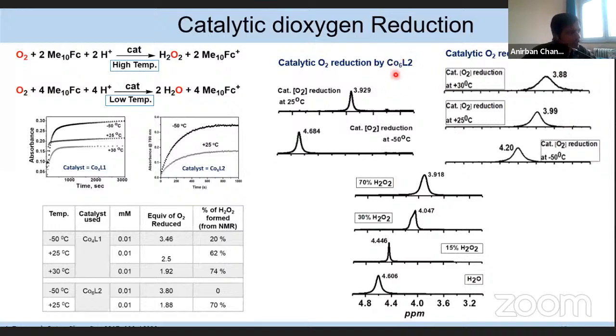For the hexanuclear catalyst at minus 50 degrees centigrade after the reaction, the NMR data shows a signal at 4.68 ppm, which exactly matches the authentic water signal. So here I conclude that for the hexanuclear cobalt catalyst at minus 50 degrees centigrade, no hydrogen peroxide forms, and it is a 4 electron complete conversion of oxygen to water. Whereas at 25 degrees centigrade, the signal is 3.92 ppm, which exactly matches the 70% hydrogen peroxide.